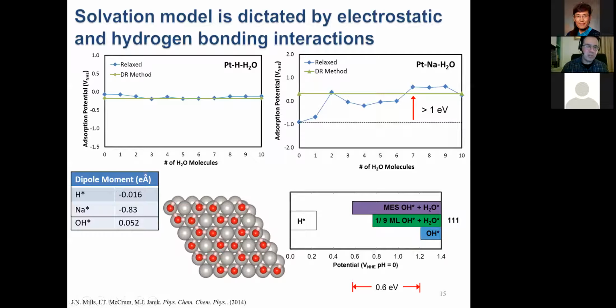And that's because hydrogen, when it absorbs to a platinum surface, is relatively neutral. It's no longer a proton. It's more like an H in a relatively covalent nonpolar bond with the surface. But it does make a big difference if I was absorbing a sodium cation, because that sodium cation absorbs, retaining a very ionic bond with the surface, retains a positive charge, big dipole moment, and that's going to interact with solvent.